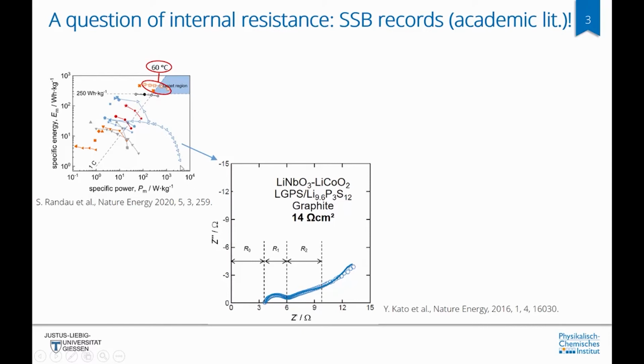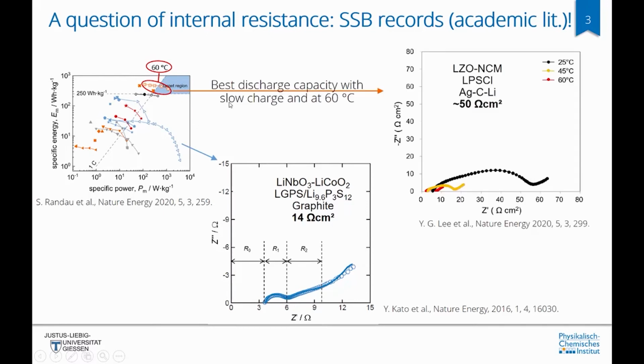Now, in order to reach this high power situation, the internal resistance needs to be very low, and it is no coincidence that this cell is the world record holder of the internal cell resistance at ambient temperature, with only 14 ohm square centimeters. Now, these high energy density cells, published by Samsung, show their best performance at 60 degrees Celsius, which is an indicator that their cell resistance still isn't quite low enough at ambient temperature to obtain the best cell performance.